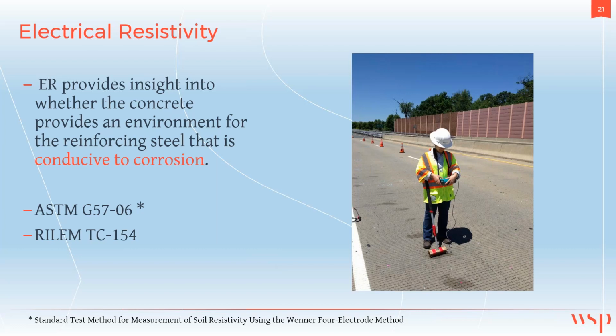Here's an example of this method being applied on a bridge deck in the field. Note that the locations where the tests are being done are pre-wetted, again, to create the electrolyte bridge to support the passing of the current, so that you're getting an indication of the concrete quality and not just resistance at the contact interface of the test device.